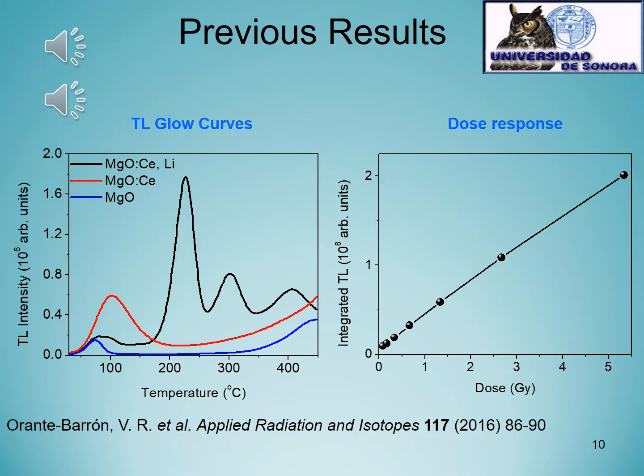We can also observe that the linearity was enhanced by around 2 times compared to the urea-based sample. This is an important result because the interval studied is increased, talking about TL dosimetry.